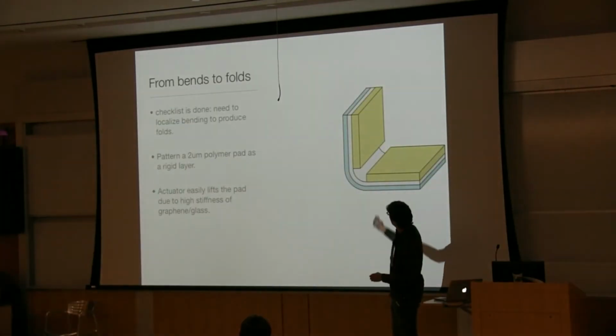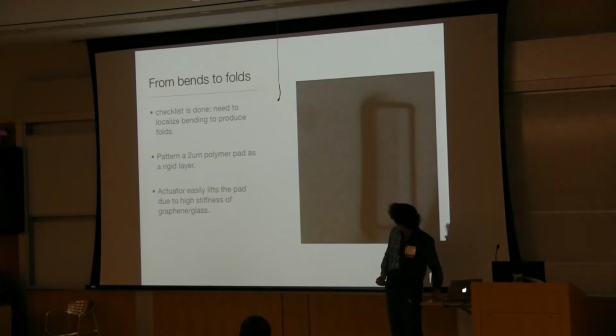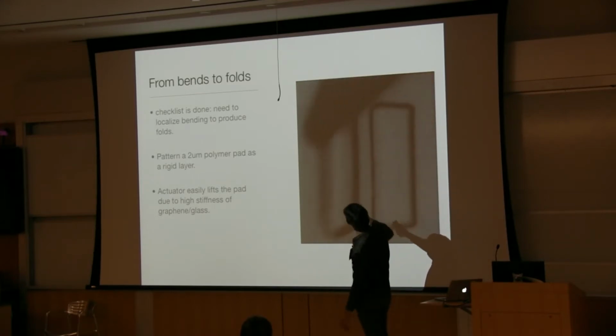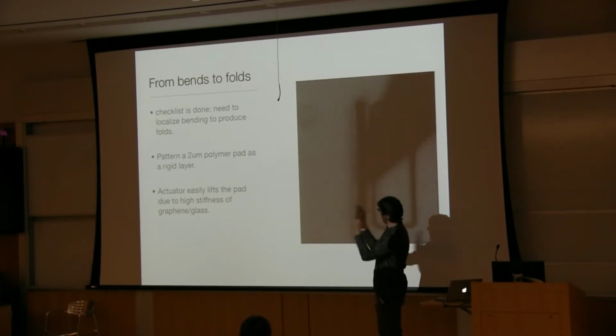Here's a micrograph of exactly what I just showed you. This is a bimorph bent at 90 degrees holding a pad up. And here's my probe tip again. I'm coming in and just poking on the hinge. And you can see that this little guy deforms elastically under the load from the probe tip and then just goes back to its rest angle position.